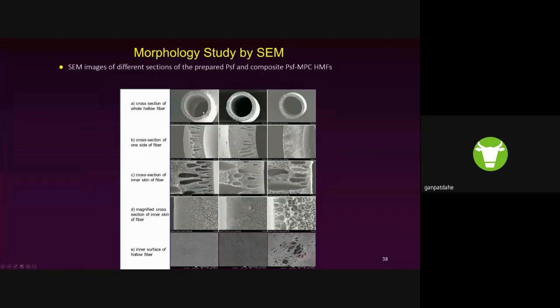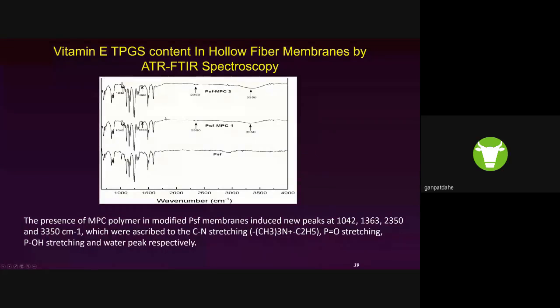For comparison purposes, we also made the pure polysulfone hollow fiber membrane with the same composition, and this is the typical microstructure we usually get from a hollow fiber. Similar to earlier studies, we also conducted FTIR of the lumen side of those fibers, and we found some new peaks at the inner side of the fiber. The peak strength is very small because those materials are present in a very small percentage.